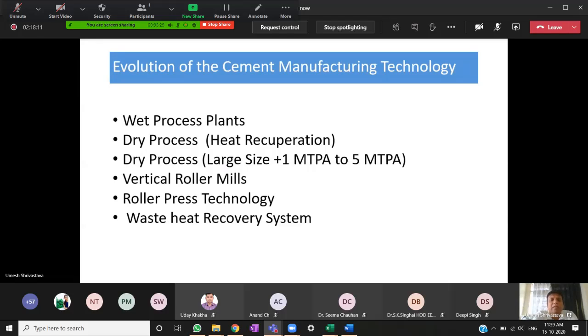And from the last 10 years, I will say that the waste heat recovery system has also come in. When we talk about any dry process cement plant, you see a lot of gases escaping, which have a heat value of around 200 to 300 degrees Celsius. Converting that heat into something productive was technically very challenging. So of late, this waste heat recovery came, and now it substitutes something like 10 to 15% of the power requirement of the plant. By that much you can conserve the power. So this is how today's cement manufacturing unit is.